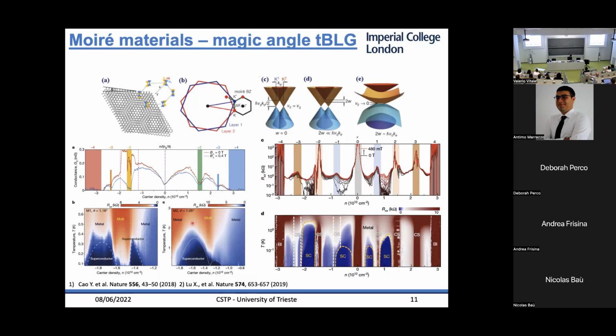And what I'm showing here is the resistivity as a function of the filling factor, gate and temperature. And so on the x-axis is this filling factor, or number of holes or electrons in the system. And on the left is temperature. So this is basically a phase diagram, right? And what you can see is that the resistivity goes to 0 for a specific value of the filling factor. And these have actually been demonstrated to be superconducting states. Whereas between these superconducting states, there is possibly a Mott insulator or a correlated insulating state.